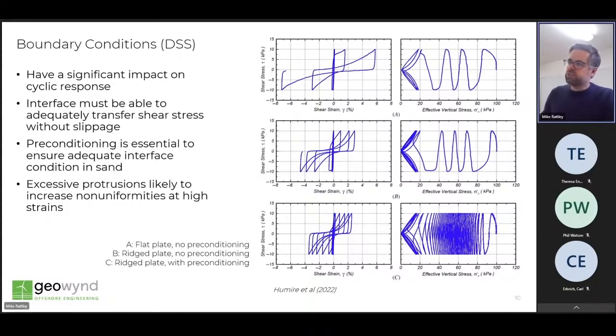The lower plot shows the same ridged platen, but this time with cyclic preconditioning applied. And you can see the significant increase in cyclic resistance and reduction in strain accumulation that's observed in this specimen. Essentially, the inference is that we're getting somewhere closer to the true cyclic response in the apparatus here by improving that interface condition. So we always need to look to make improvements to the boundary conditions of the test.